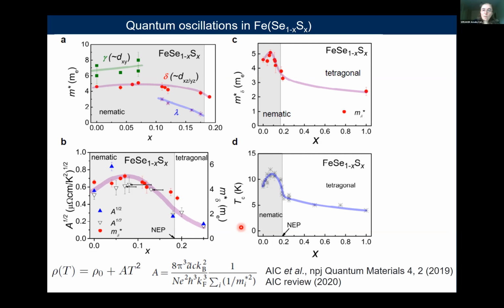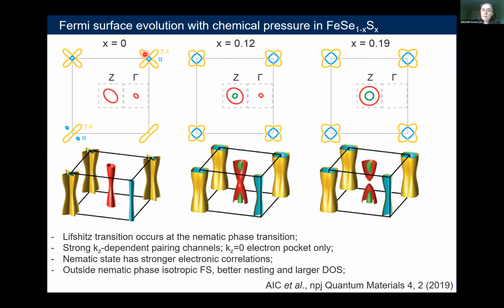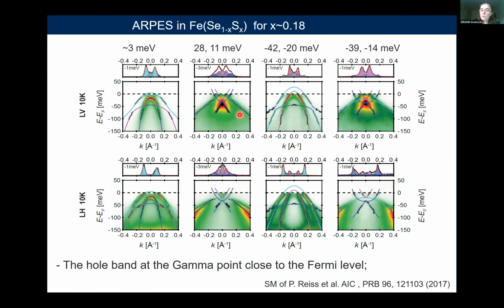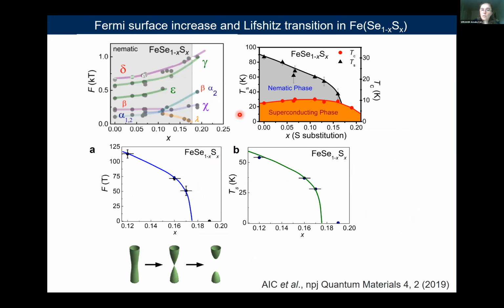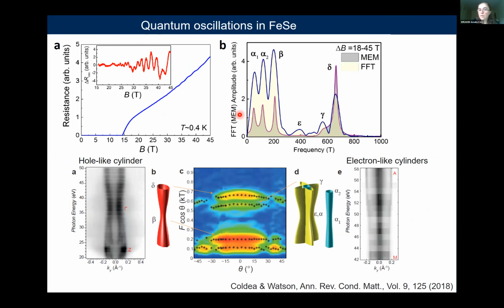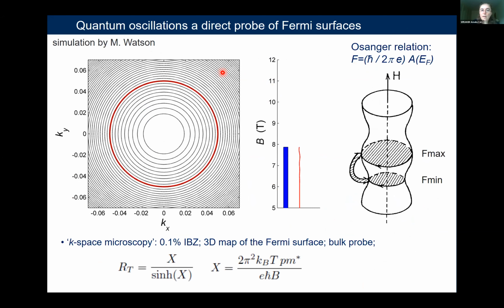So the position, so the ARPES, just before I go to ARPES, just again, so we see this evidence of this band here, just that it follows similar trends to the delta band. This is the hole outer orbit of the hole band, so this is the outer orbit of the electron band. So now when I think about these orbits, for me are these flower-shaped orbits, and they contain some DXY character. So they are not pure DXY, as you would think in ARPES, but because we measure orbitally averaged orbits, they will have a bit of DXY character as you go around the Fermi surface.